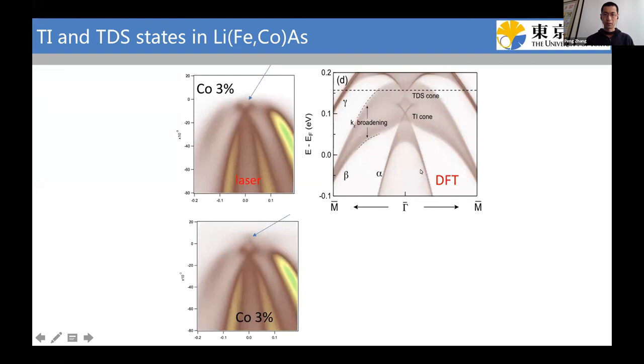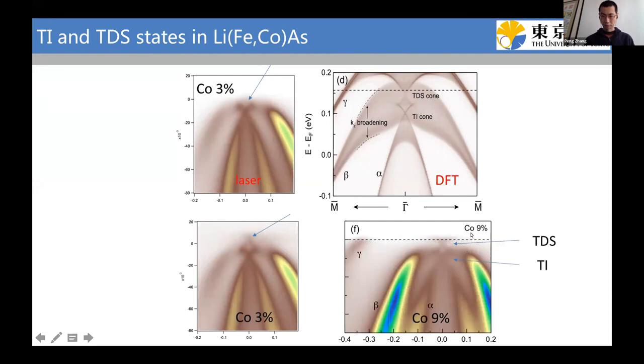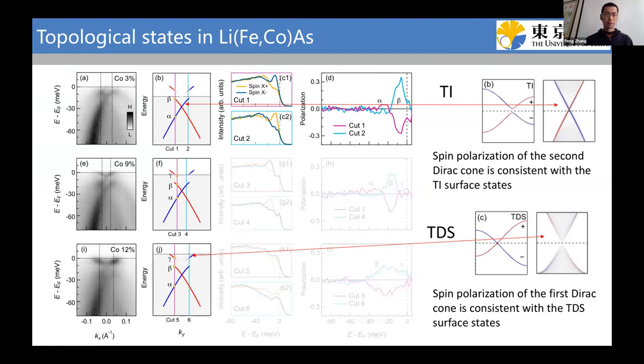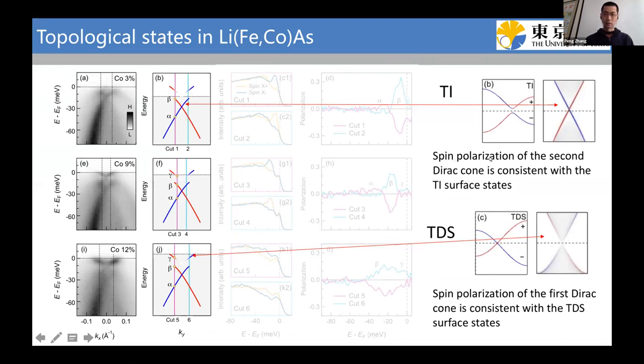We compared with the calculation, and we find the lower one is the topological surface Dirac cone, and the top one is from the Dirac semimetal cone. Also, it's very easy to dope lithium iron arsenic with more cobalt, so we further checked 9% cobalt doping. In this data, without any other process, we can clearly resolve the two Dirac cones. The lower one is the surface Dirac cone. The top one is the bulk Dirac cone. If we compare this data with the calculation, they are basically the same. We also checked the spin polarization of the two Dirac cones, and we found the spin polarization is consistent with a simple k·p model.